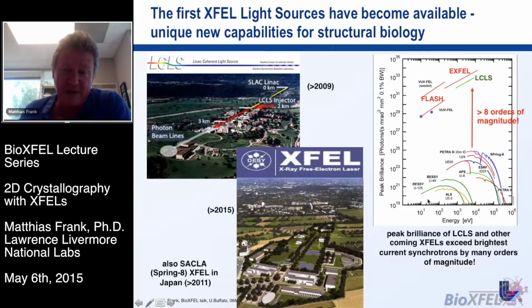So this plot on the right just shows what a big step up in brightness this is. The bottom axis is energy, and down here is like 1 keV, 10 keV, and around 10 to 12 keV is where you want to be for crystallography. And the peak brilliance on a logarithmic scale is basically a measurement of how many photons you can put in how small a spot in how short a time. Down here, these colorful curves are basically the modern synchrotrons we have, the brightest synchrotron sources. And there are 8 or 9 orders of magnitude in peak brilliance difference.